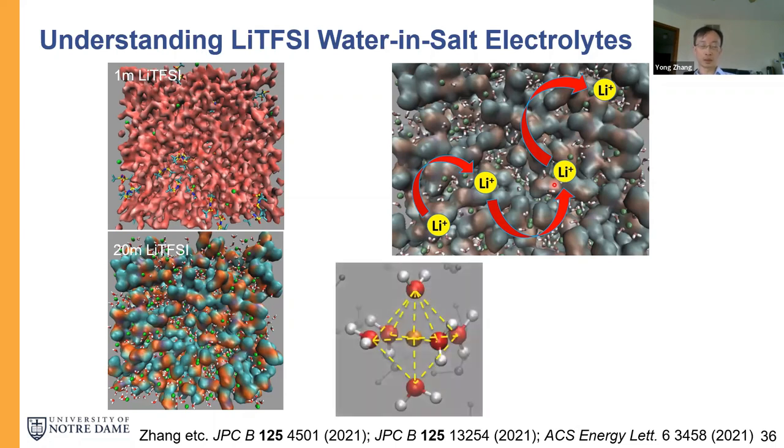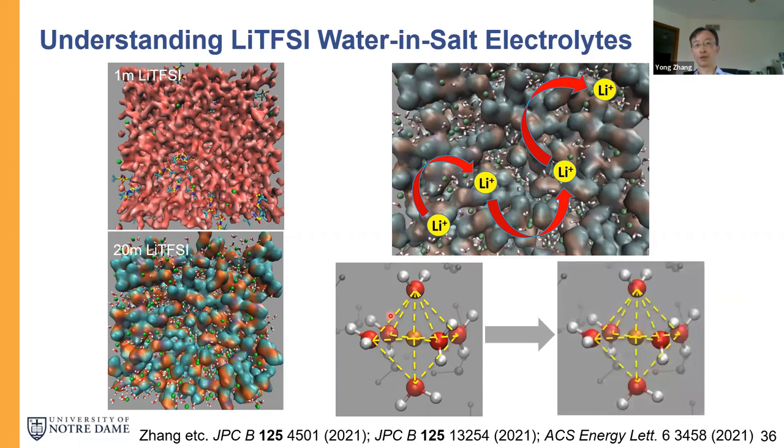Then when we add zinc into this solution, the lithium TFSI water structure doesn't change much. But it's interesting that zinc is coordinated by water only, even at high concentration, and this structure is super stable. So the conduction mechanism for zinc is totally vehicular. This structure doesn't really change during our simulation of about 100 nanoseconds.